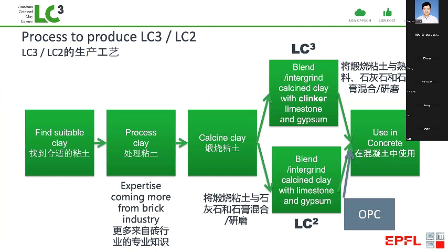Now you can use these calcined clays in two ways. You have to find the clay, you have to process it, and then you have to calcine. And then you can either blend all the ingredients together, the calcined clay with the clinker, the limestone, and the gypsum, and this is what we call LC3. Or you can make an additive. You can add at the concrete level, where you intergrind the calcined clay, limestone, and gypsum, and then you add it to OPC, and you're using concrete.